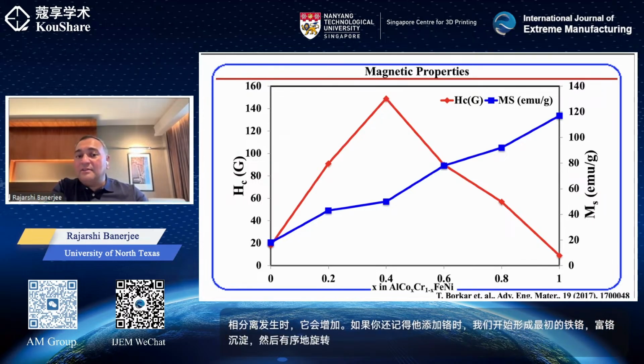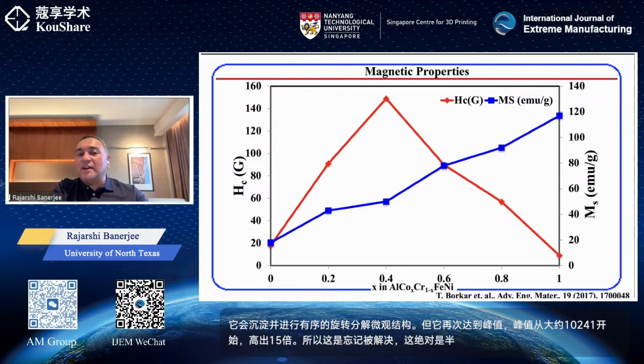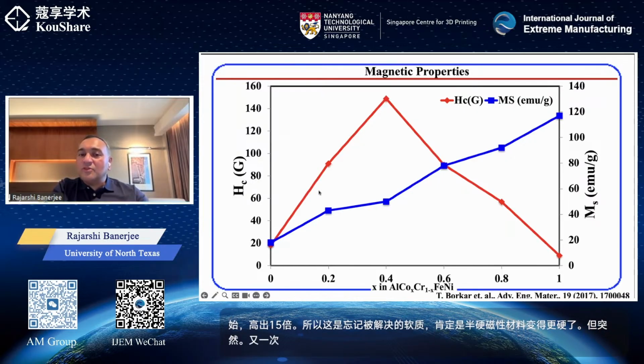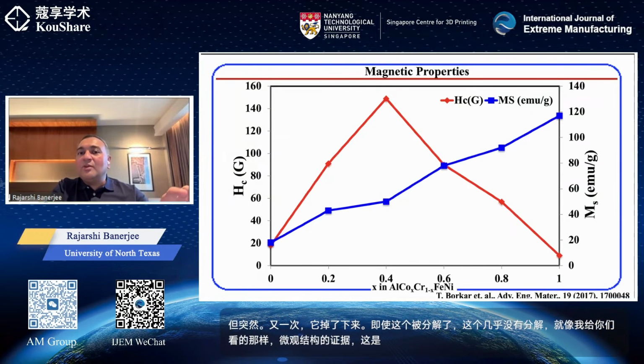Again, the peak value is going from about 10 to 140, it's 14, 15 times higher. So forget being soft, this is definitely a semi-hard magnetic material, getting close to being harder. But suddenly, again, it falls down, even though this is decomposed spinodally, as I showed you the evidence of that microstructurally. So it's a very interesting interplay of the magnetism with the microstructure.